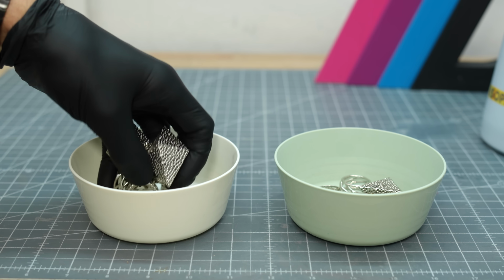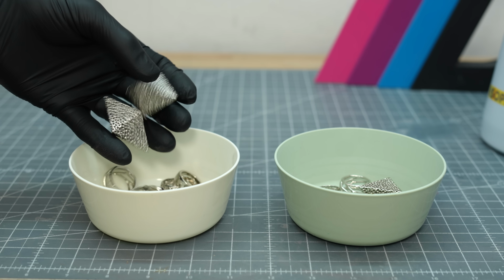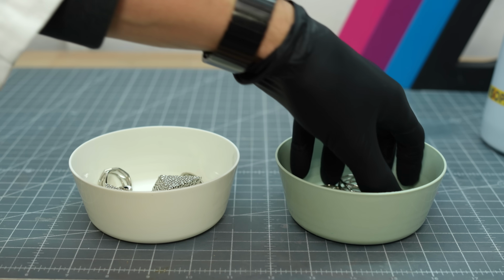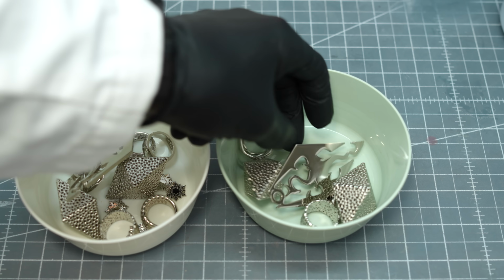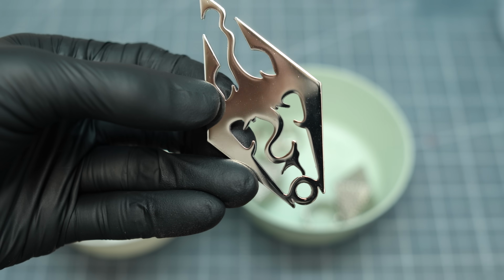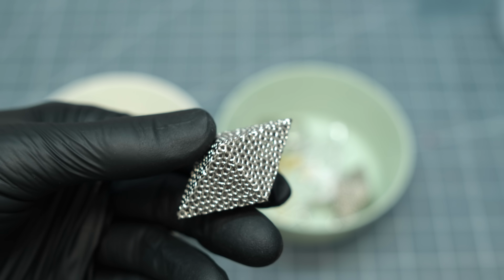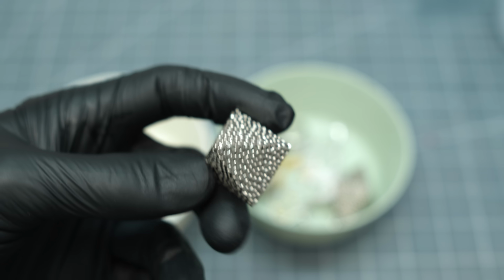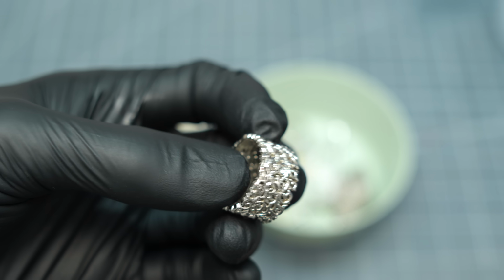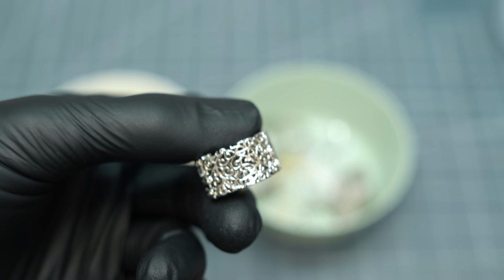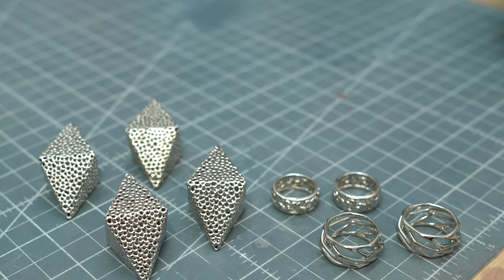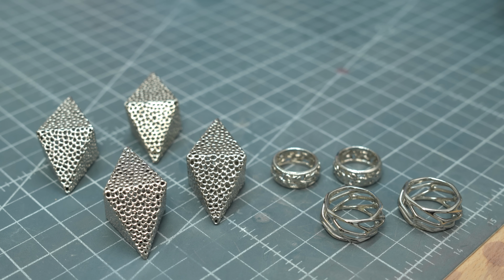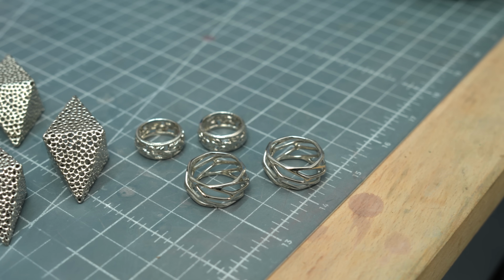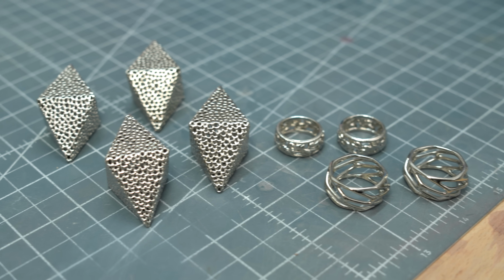It's possible to add additional layers of different metals which are usually thinner. The order of these layers is also important. For these pieces I applied a nickel barrier layer to prevent diffusion with the gold and silver. However, nickel electrolyte is toxic and not a good choice for jewelry because it's also allergenic. A much better alternative is palladium. I ran out of it, and since I'm using these pieces for demonstration purposes only, I didn't use palladium. If in doubt, you can also apply gold and silver directly onto the copper.